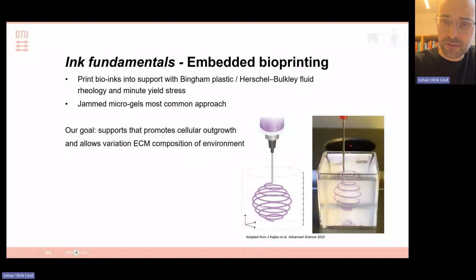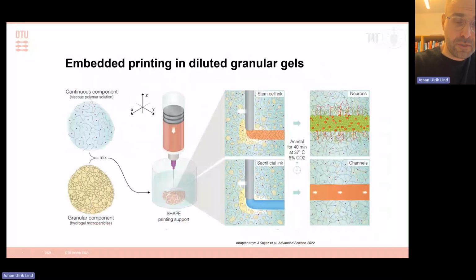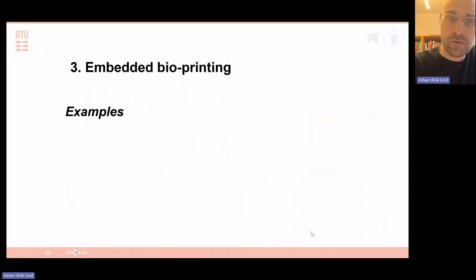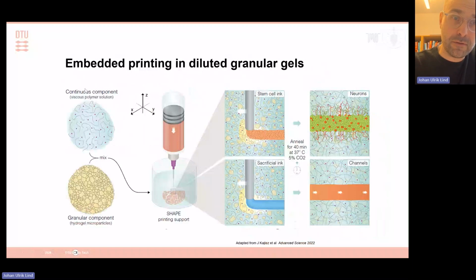This was a collaboration with the engineers and was led by Janko, who's the first author of this paper. The idea was as follows. We take one of the granular components that are commonly out there and optimize a little bit of that. In our case, we focused on alginate. And then we were curious, instead of jamming the particles into a low viscosity solution, if you add a continuous component here to the granular gel where you have a high viscosity solution, then we might be able to get more space around these microgels, and use this component to control the ECM. We studied neurons in this case, and we're interested in seeing whether we can have a system where we can simultaneously promote growth and outgrowth of axons from the neurons.